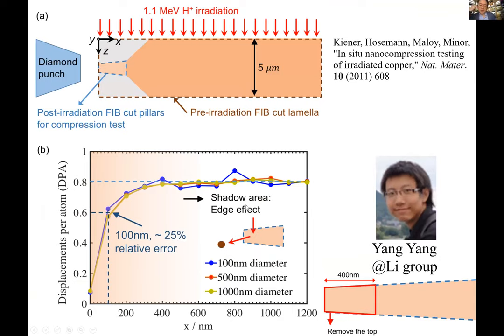So we have used the IM3D code to look at, for example, people trying to make these nano pillars to do mechanical compression experiments. People use an ion accelerator to generate some DPA in the material, and then later FIB out the material to do the small scale sample test.